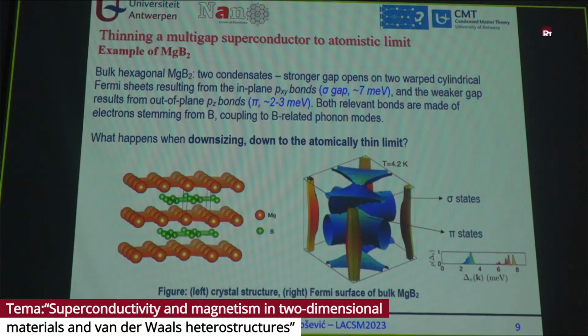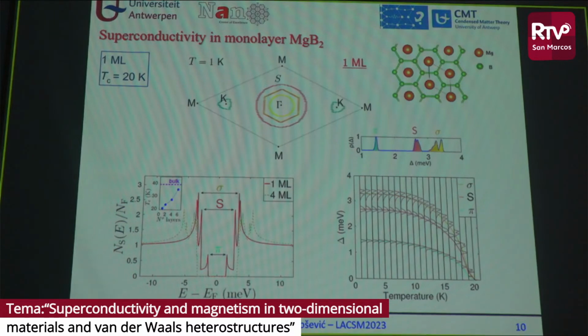Okay? So now the question we were asking is, what happens when we try to thin this material to two dimensions? So this is what you get for a monolayer magnesium diboride. Again, this is the magnesium atom, these are the boron atoms. The surface band arises. The surface band is related to pz orbitals of magnesium at the top surface. And instead of a two-gap superconductor, we get a three-gap superconductor. So this is the pi band gap, this is the sigma band gap, and there is the surface band gap, the third. And these three gaps, you have to look at this spectrum along this line, persist throughout the temperature range all the way to a Tc of about 20 Kelvin in this case.